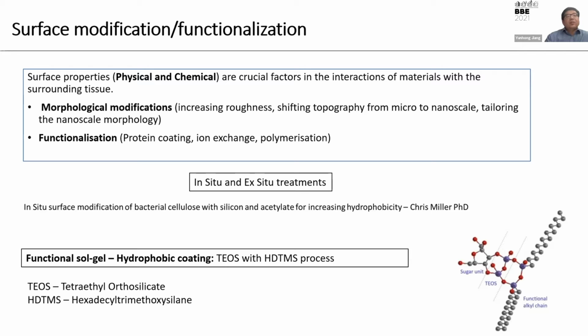And the functionalization means to introduce a certain functional group on its surface or change its own surface chemistry. We can also modify the bacterial cellulose during the growth. We call that in-situ modification, or after growth, we call the ex-situ treatment or post-treatment. Currently, my PhD student Chris Miller is working on in-situ modification of the bacterial cellulose using silicon and acetylate. You can find more information from his poster.